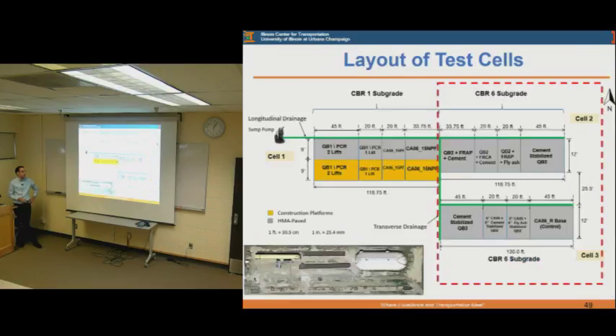So that's what we were investigating in the field, is to mix the quarry byproduct with cement, 3% cement or 10% fly ash, and then have some test sections where the quarry byproduct is blended with RAP or with recycled concrete, with cement or with fly ash, as well as some test sections that only have quarry byproduct by itself, cement stabilized. And we were investigating the effect of changing the type of quarry byproduct. So we had 2 different sources of quarry byproducts. That's why you see the QB2 in cell 2 here, and then the QB3 in cell 3.